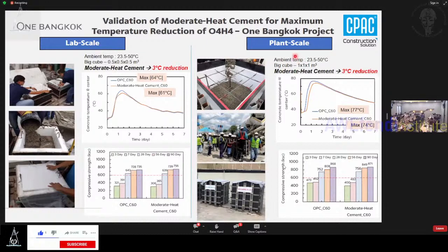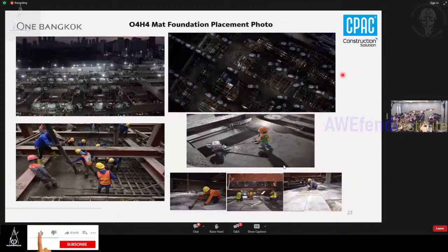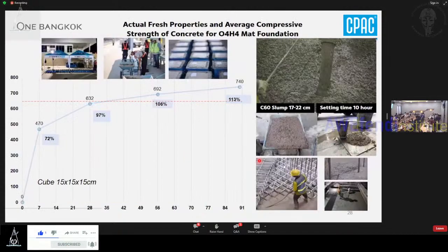And after that, we moved to plant scale. We cast 1 cubic meter and compared the temperature peak again. So we got the number again, 3 degrees Celsius, quite close to our lab test. So everyone was happy with this one. So we went on and cast the concrete. You can see the number of trucks here, a lot of trucks, and we have pumps alongside the trucks. And as I mentioned, after they cast, they finish the concrete. And this one is what the concrete looks like and the strength development of the concrete that we got.